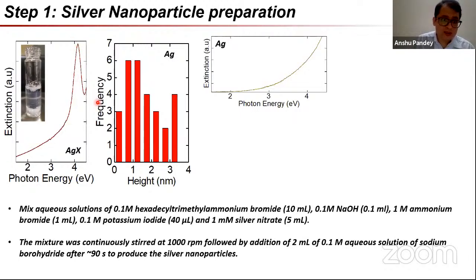This is the spectrum of these original silver halide particles. So they are slightly turbid sometimes, but we prefer to work with systems which are reasonably transmissive. Subsequently, borohydride is added. That leads to their conversion to silver. Now, once we have silver, you can see this was again a question which was asked very early on, what was the size distribution.